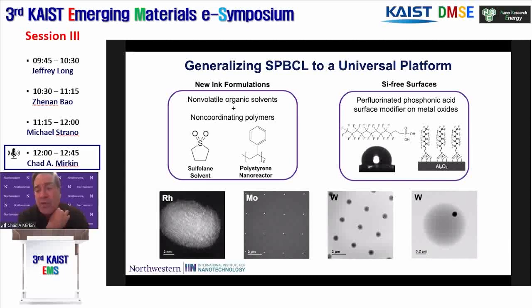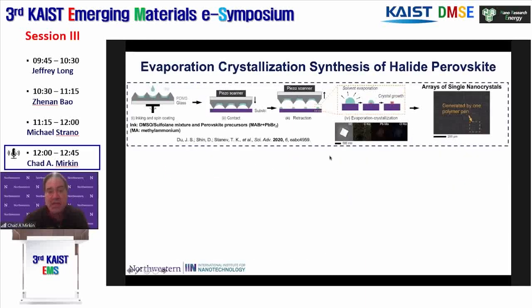Certain materials would react with the underlying substrates, or the substrates that we wanted to pattern on weren't appropriate because they didn't have the right hydrophobicity. For example, if we take alumina, we can modify with this perfluorinated phosphonic acid. That gets us a very hydrophobic non-stick type material that allows us to generate very nice nanoreactors. And now we can begin to move to materials like tungsten, shown below.